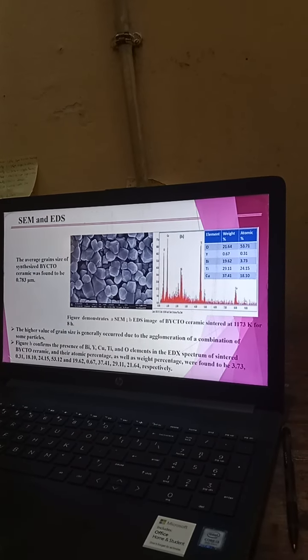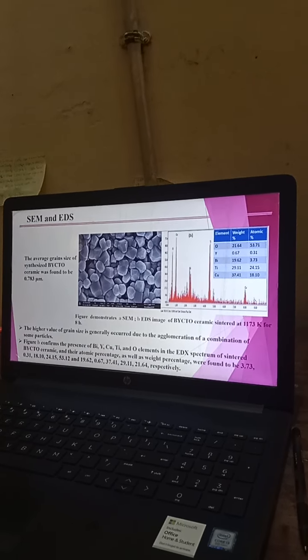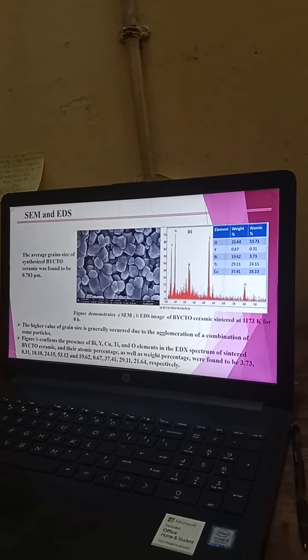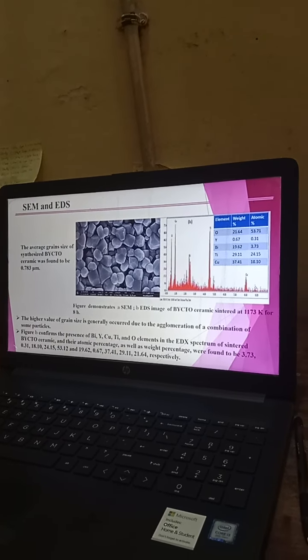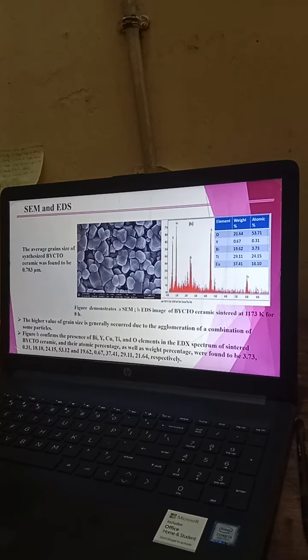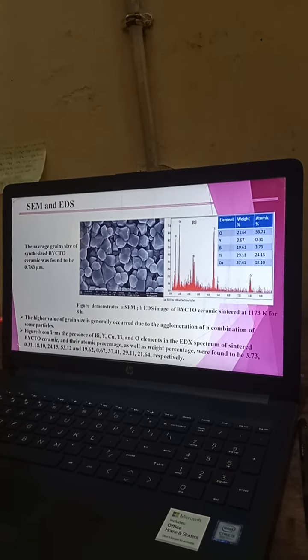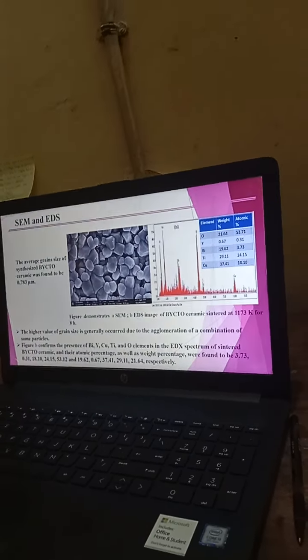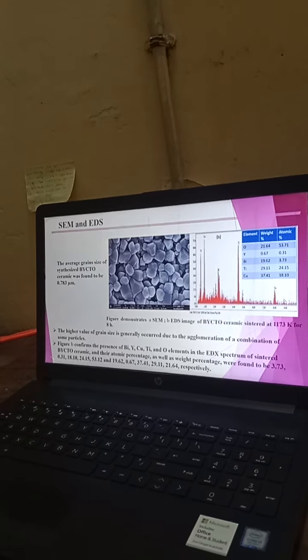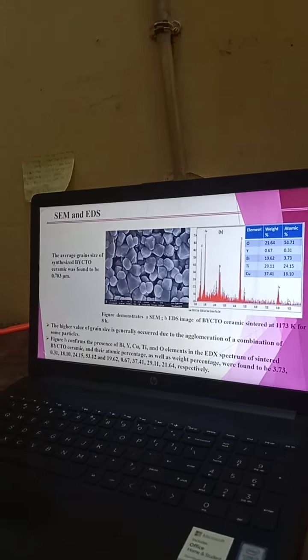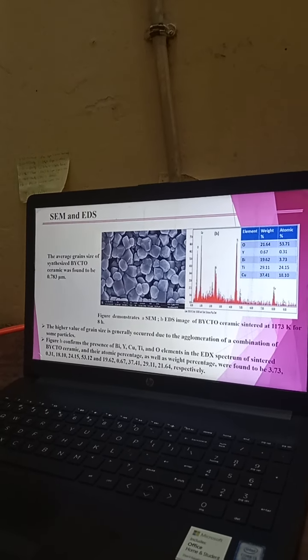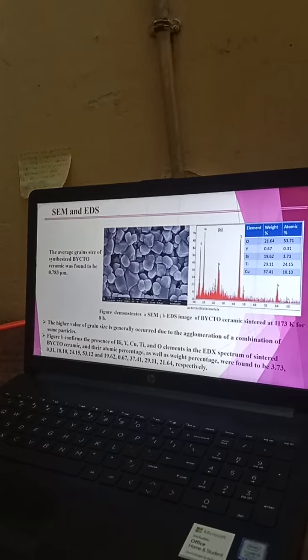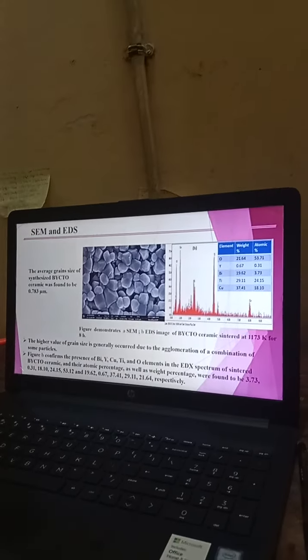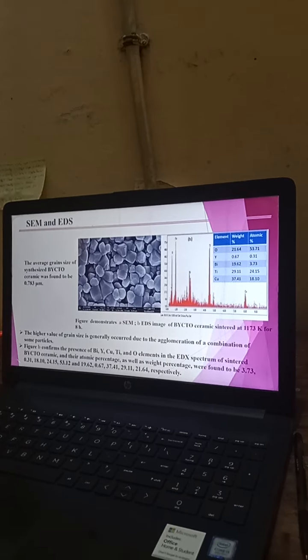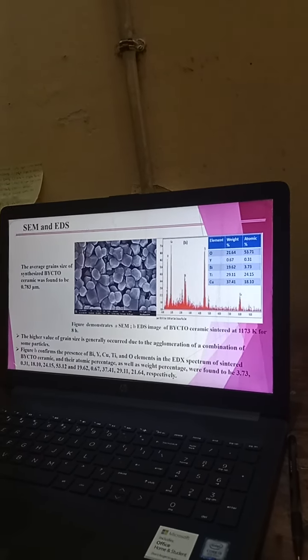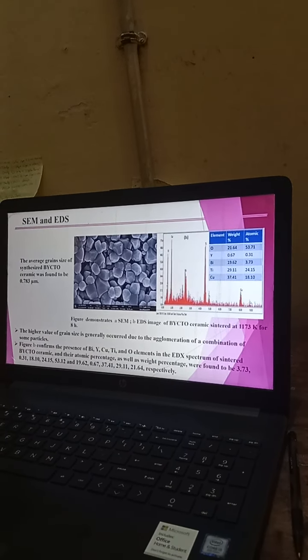SEM and EDX. Figure A shows the scanning electron microscope image, and B shows the EDS image of BYCTO sintered ceramic at 900 degrees centigrade for 8 hours. From figure A, in the SEM image, the particles look polygonal, and we have also seen porosity in the material, which is due to the evolution of some gases during citrate nitrate combustion when we synthesized the material.